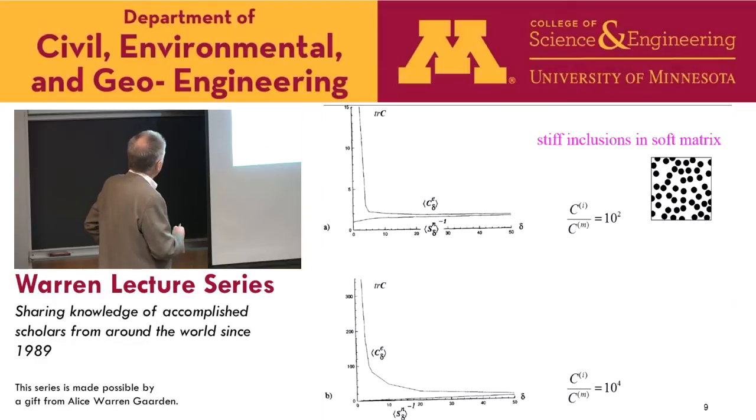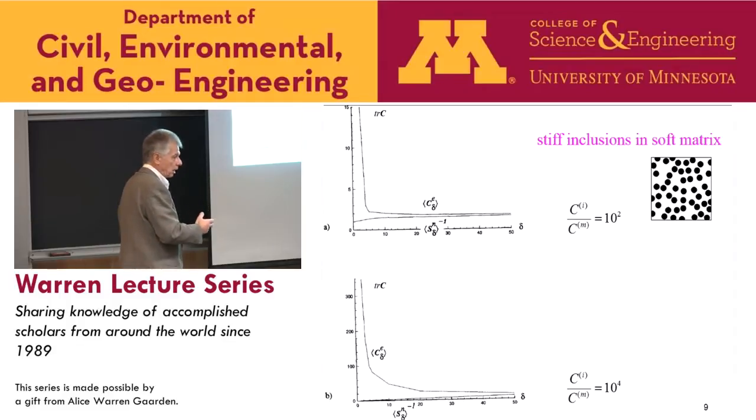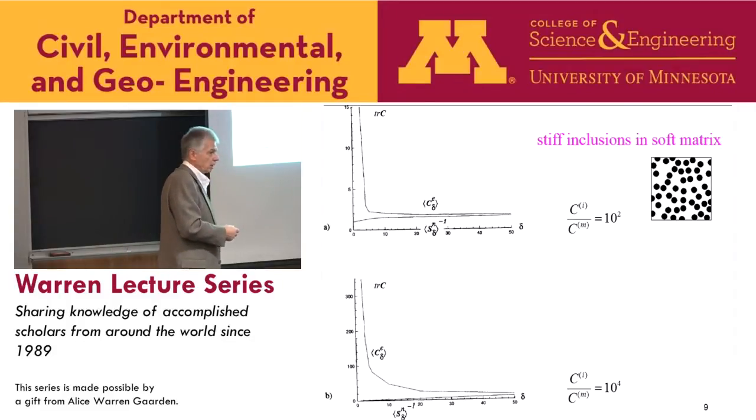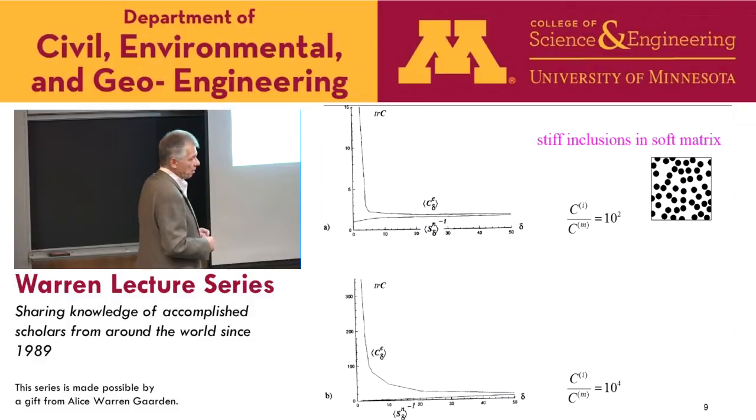And if I go with this Dirichlet bound, or displacement control bound, or essential, I'm using here E superscript, then I have this result for the trace. Strictly speaking, I have scatter. For any given window, I have to solve the problem by some computing method, finite element, finite volume, whatever your preference is. In principle, you have to run it in Monte Carlo, get the statistics.